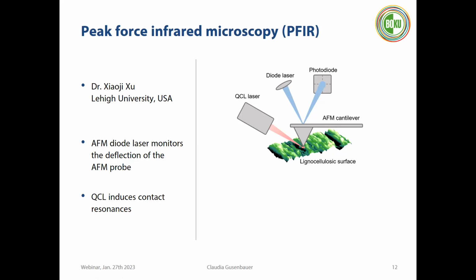But in the setup, there's also a laser which is focused between the tip and the sample. And due to the laser, we have thermal expansion of our sample, and we can measure this thermal expansion with the AFM tip. And this thermal expansion is depending on which chemical component is mapped between the tip and the sample. So we can not only measure the height information of our wood cell wall, but we also get chemical information based on the thermal expansion, which was driven by the laser, which is focused between the tip and the sample.